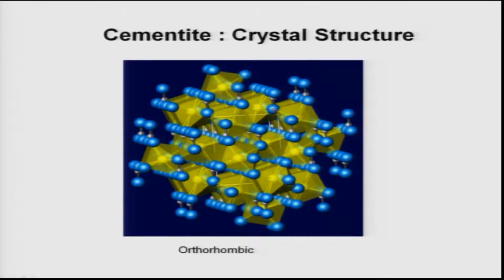That is what you see here. These corners attach the octahedra. That is how this complex orthorhombic structure forms. So basically the carbon atom goes to the octahedral voids in the BCC iron lattice. That is how it forms, distorting the lattice and leading to the formation of the orthorhombic structure.